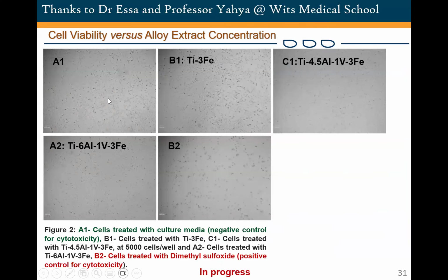But if you look at our alloy extract, you can see that not all the cells died, but we see that some of the cells, the rounded shape of the cell shows that they are dead. In all of the cases here, you would see that we have a situation where some of the cells died and a majority of them are still healthy. These images are just showing what has happened in terms of positive control and negative control.